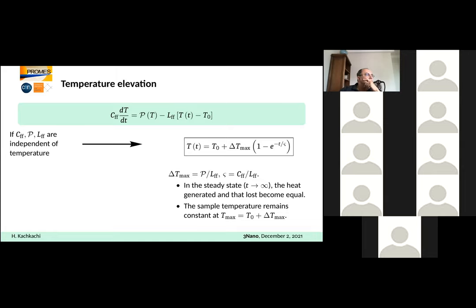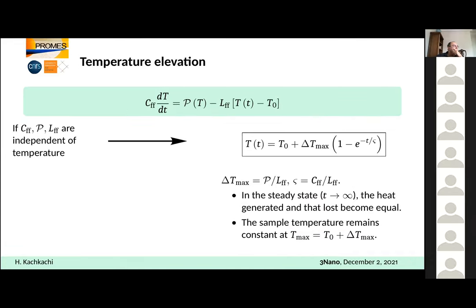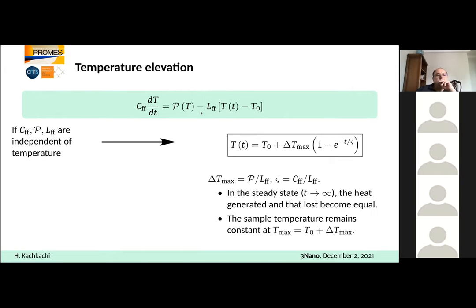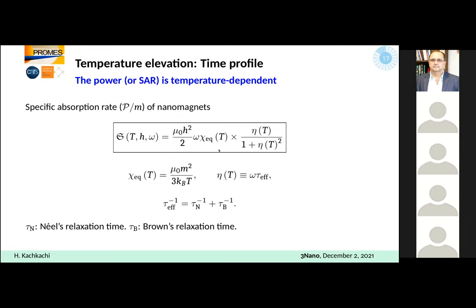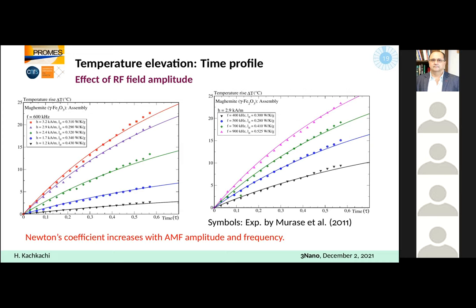So there are three stages. And this equation just ignores the intermediary stage, which is the diffusion within the assembly. This is assumed to be rather fast. So what remains is the injection of energy from the magnetic field and its loss towards the environment, right? But the question is how to characterize this coefficient. The main objective behind plotting this data is to encourage some experimental groups to perform further experiments to characterize such a coefficient, because here it's used as a kind of phenomenological parameter.